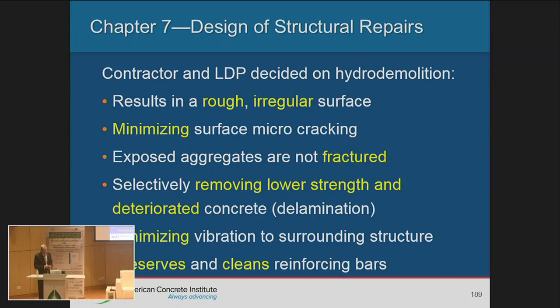So the contractor decided to go with the hydro demolition, which results in a rough, irregular surface. It minimizes the surface micro cracking. It exposes the aggregate so they are not fractured. And if you have low strength concrete, it will remove that concrete. It minimizes vibration to the surrounding structure, and preserves and cleans reinforcing bars, which is important. So if you have any bars, because of removing 90 millimeters, you're exposing your reinforcement. And we mentioned that bars were corroded, so it will clean those bars. And it will preserve them, and will not damage those bars.